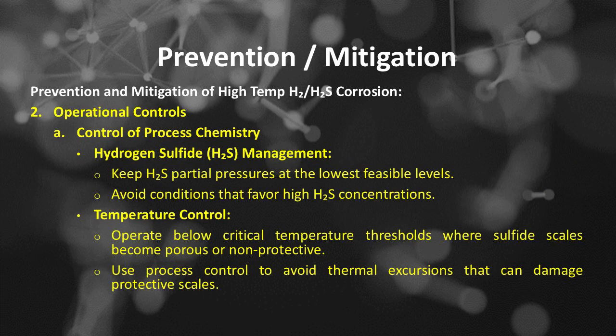substrate. Number 2 of prevention and mitigation methods is operational controls. A: control of process chemistry. The first is hydrogen sulfide (H₂S) management: keep H₂S partial pressures at the lowest feasible levels, avoid conditions that favor high H₂S concentrations. The second is temperature control: operate below critical temperature thresholds where sulfide scales become porous or non-protective, use process control to avoid thermal excursions that can damage protective scales.